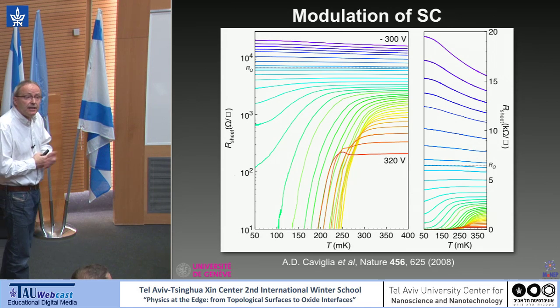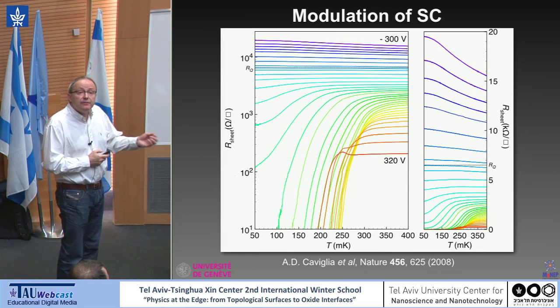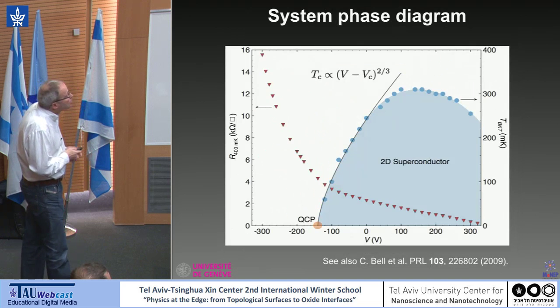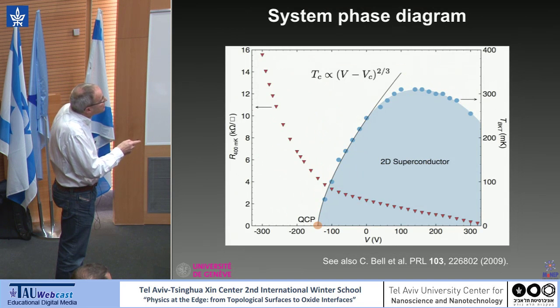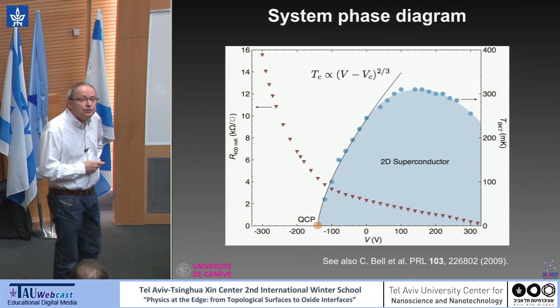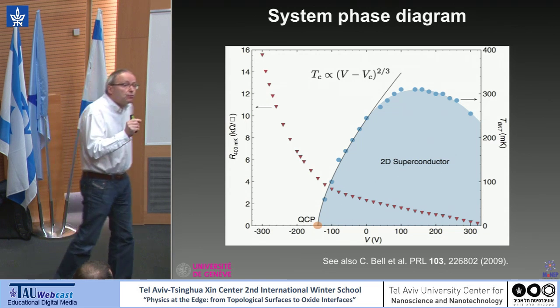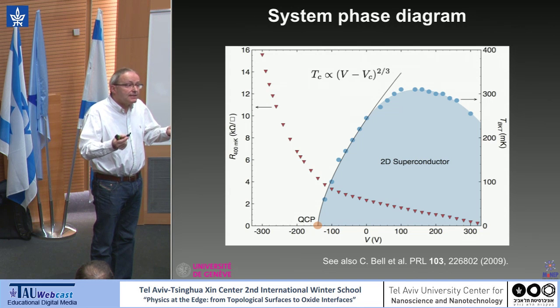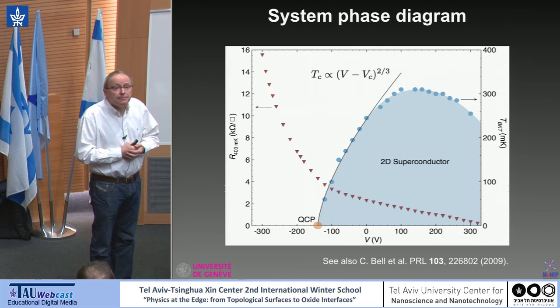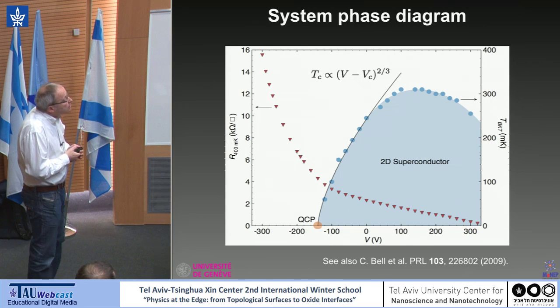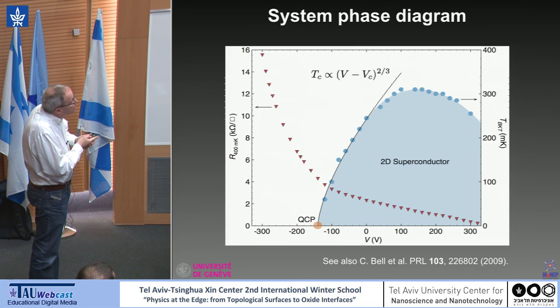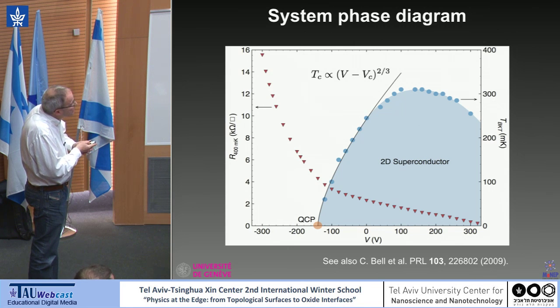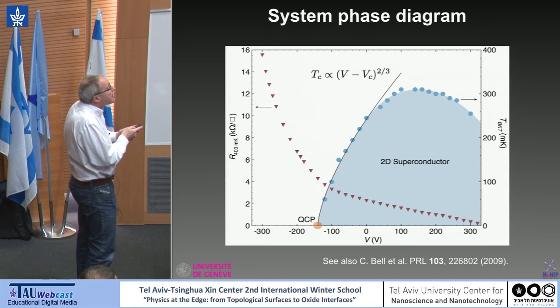With this, you can define again a TC, and now you can plot TC versus the gate voltage. This is what you see here with the superconducting pocket. By the way, I wrote 2D superconductor because I forgot to mention before, but when the superconducting coherence length is larger than the thickness, your system is 2D. Now, when we saw this at the time, we tried to look at the dependence of TC close to this quantum critical point. We saw that TC was going as the voltage minus the critical voltage, which is here. It could be carrier density. It's linear in this regime, to a power 2/3.